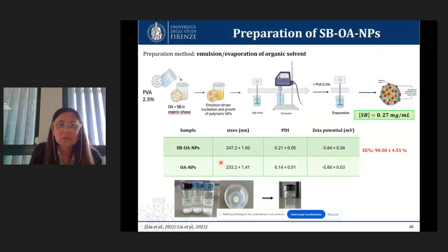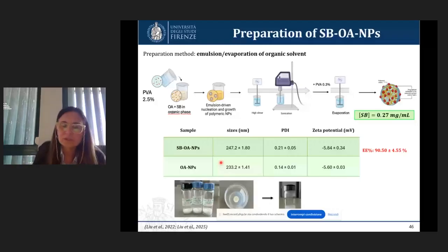Nanoparticles are due to the presence of hydrophobic interaction between the molecules of oleanolic acid, but also hydrogen bond interaction. We produce nanoparticles using emulsion evaporation of organic solvent, and to stabilize the nanoparticles, we used polyvinyl alcohol. The silibinin inside oleanolic acid nanoparticles improved the solubility until 0.27 milligram per milliliter.